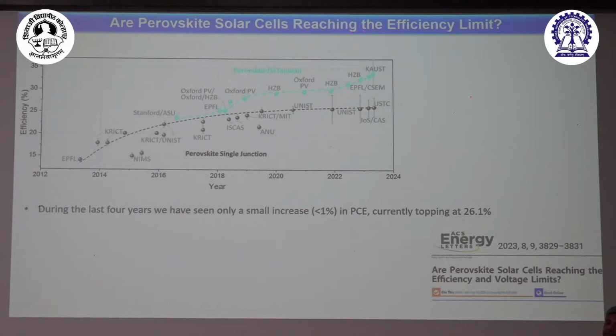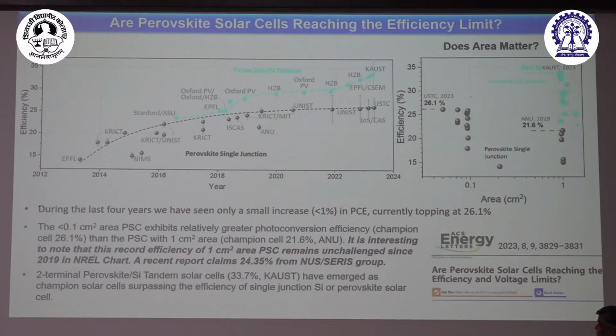How did they get it? They went from 0.1 centimeter square to 0.05 centimeter square. So that's not the thing. We have seen only small increases. The 0.1 centimeter area exhibits relatively greater efficiency, and this is now the champion efficiency, right, than the PSC with 1 centimeter square.